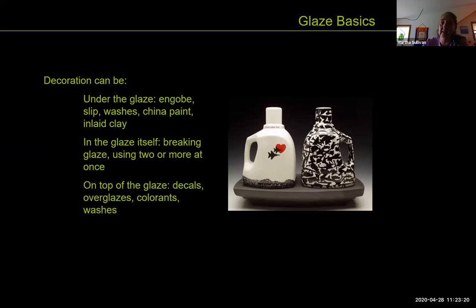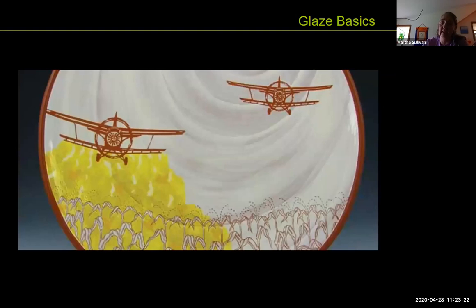And so this is like Stacy's decals that were that burnt red. The white and the yellow are glaze underneath, and then there is this iron transfer that's gone onto the surface. So it's an interesting way to get really graphic details on your pot. Again, the glaze has already been fired, and this is in a follow-up process.